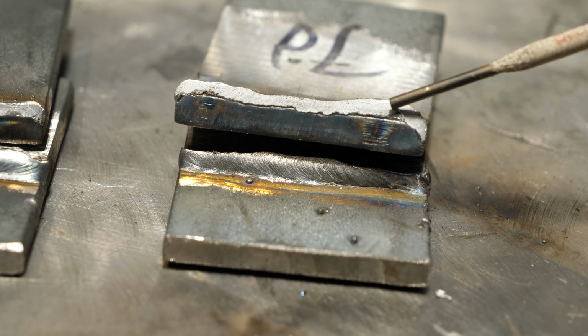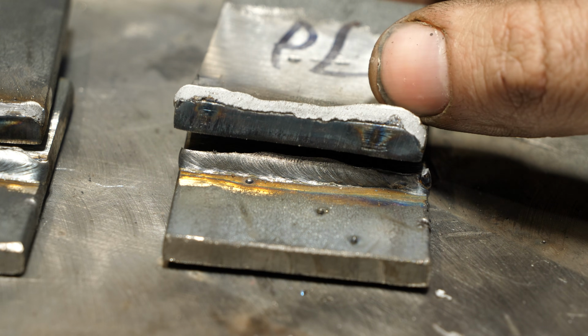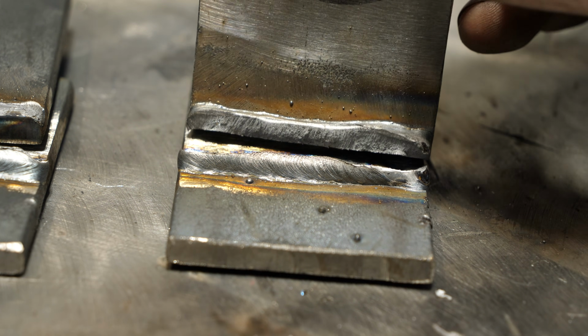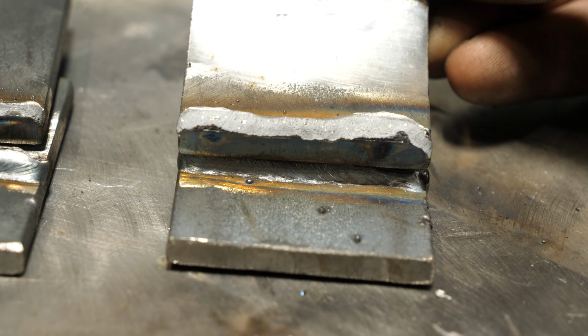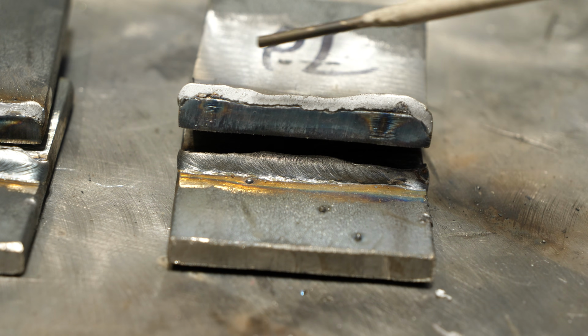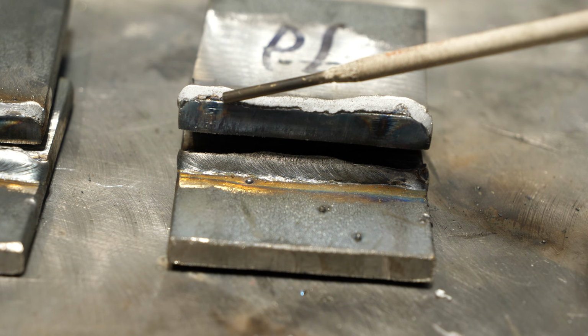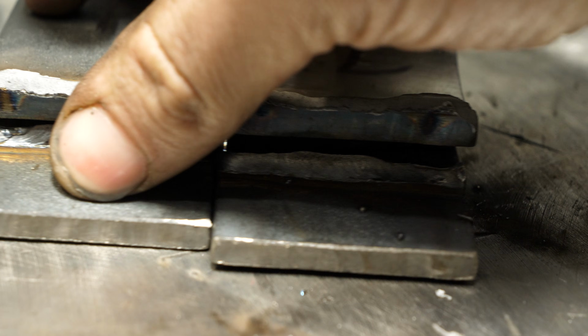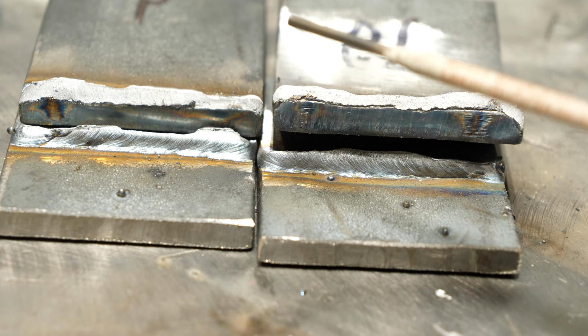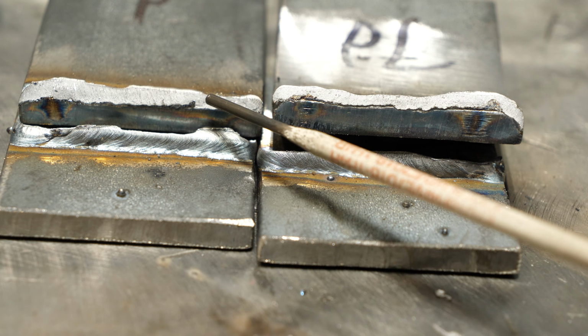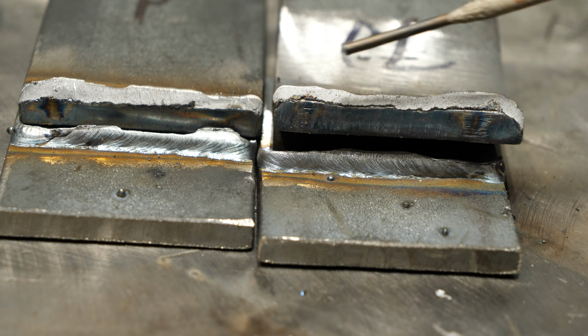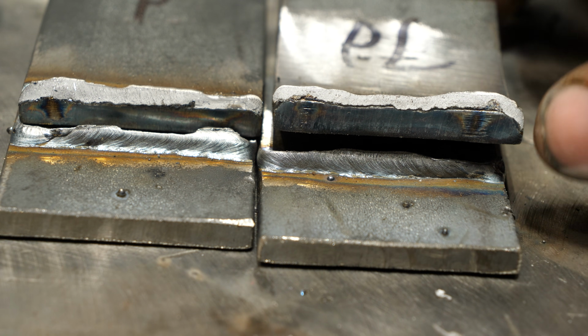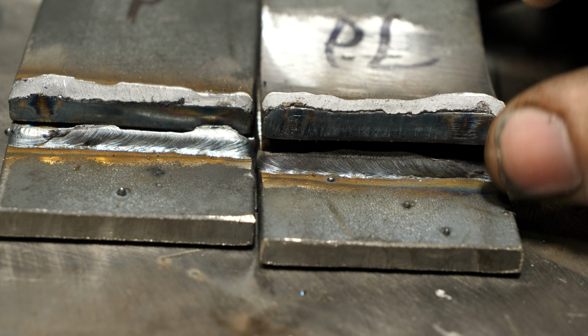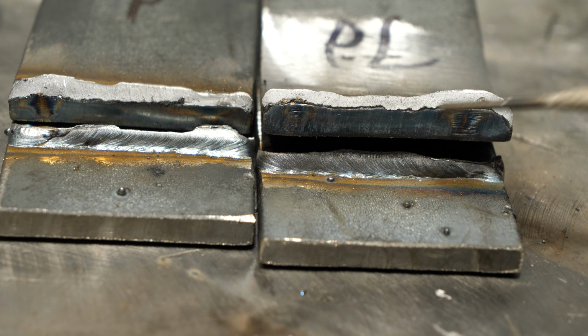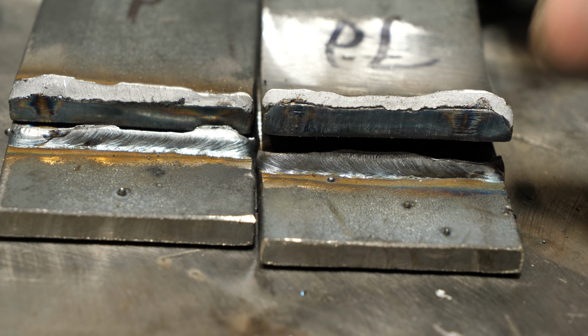So all interesting stuff. The reason I would say that this was so much stronger really had to come down to no lack of fusion that was significant. When you look at this, that complete area didn't even fuse. So it's just a more consistent fusion weld. It has deeper fusion in parts, and then this little bit really helped it.